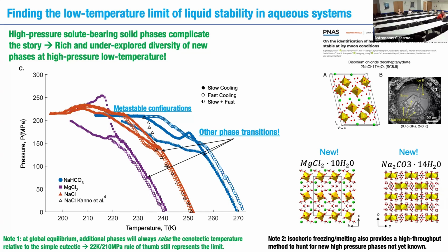And then in the MgCl2 system and the sodium bicarbonate system, we went to Grenoble and got some time at ESRF and did some single crystal XRD. We haven't published these structures yet, but found interesting new structures corresponding to each of these phase transitions. And I think we're just really scratching the absolute tip of the iceberg here in terms of the diversity of potentially hyperhydrated, high pressure, low temperature phases that exist out there, right?